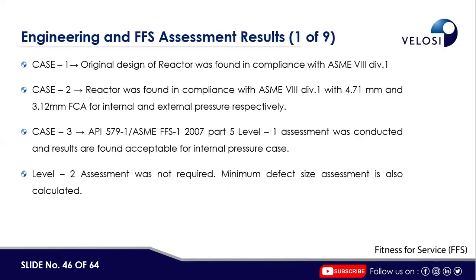In Case 1, basically results now. Case 1, the original design of the reactor was found in compliance with ASME Section 8 Division 1. Case 2, the reactor was found in compliance with ASME Section 8 Division 1 with 4.71 mm and 3.1 mm FCA, future corrosion allowance, for internal and external pressure respectively. Case 3, API 579-1 Level 1 assessment was conducted and results are found acceptable for the internal pressure case. Level 2 assessment was not required since the defects were accepted in Level 1.